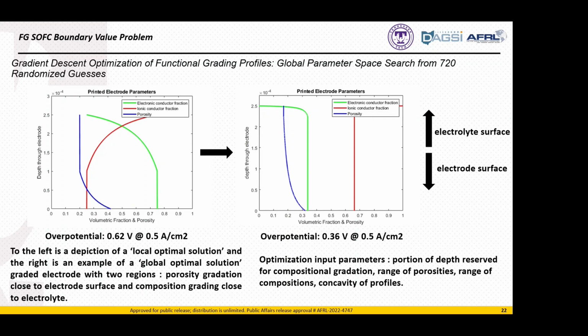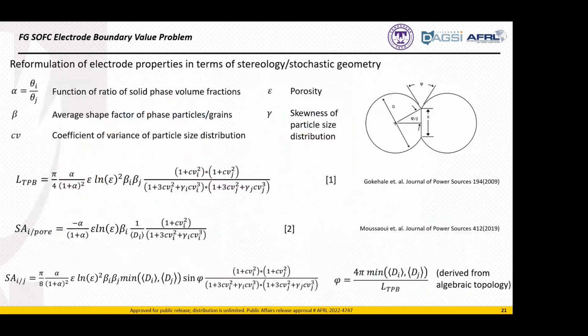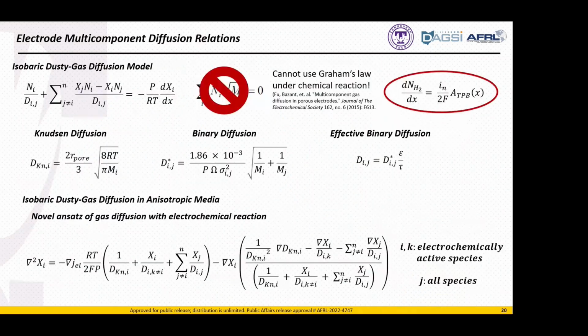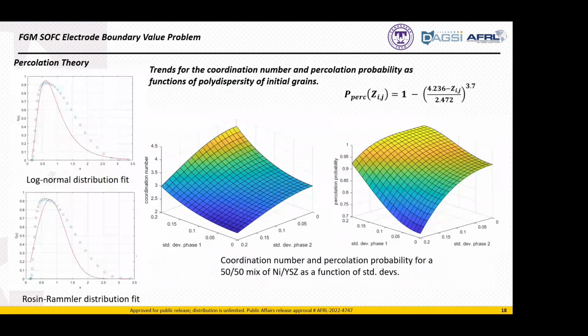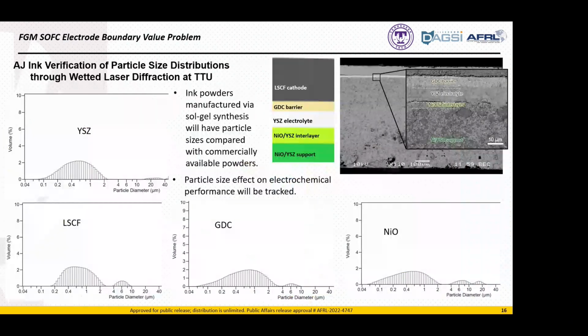There are so many questions. One of the slides, I just want to make sure that you corrected. When you were looking at the composition of the anode itself, you talked about particle size distribution from zirconia, and you showed nickel. That really should be nickel oxide. Yes. On which slide? You tell me, I don't remember the number, but you talked about composition of the particles, because typically, especially for what you call nickel YSZ, the starting point to fabrication is nickel oxide. Oh, yes. When we were doing the particle size analysis, yes. Right, nickel oxide here.